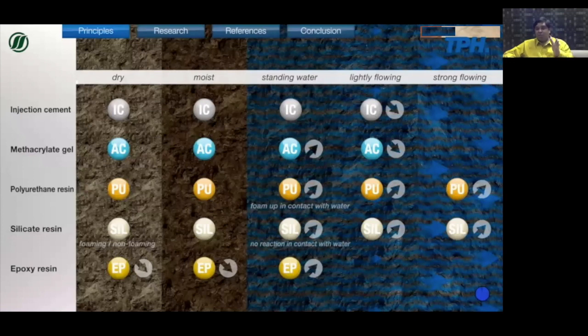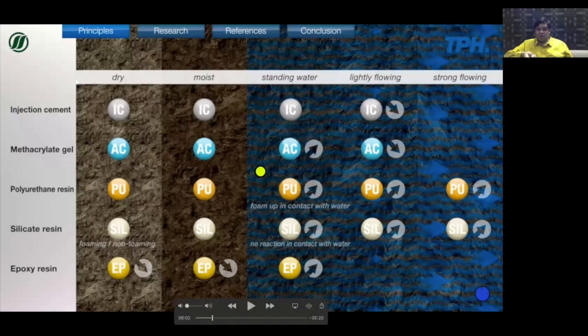Now the problem comes, both in structures as well as in soil, when you have things like standing water. Even in case of standing water, the effect of cement starts going down because it has more water to contend with. That changes the water cement ratio and hence the efficiency of the materials. But in such cases, the effectiveness of methacrylate gels keeps on increasing. Polyurethanes are also very interesting to use here because they foam up in contact with water. So it can go inside and consolidate even in case of water, or lightly flowing water, very well.